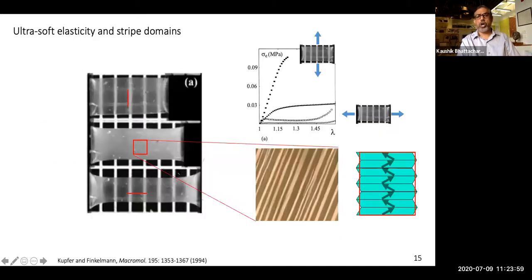And this is what you saw manifest itself in this soft behavior that I described. So this material was created by Finkelmann by making all the directors lined up here. So it's uniform. And the signature of this is that this material is translucent. When I start pulling along this direction, this director wants to reorient and become horizontal, but as it does so, it tries to shear the material.